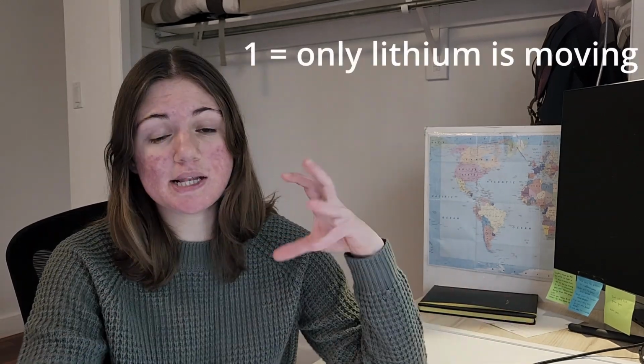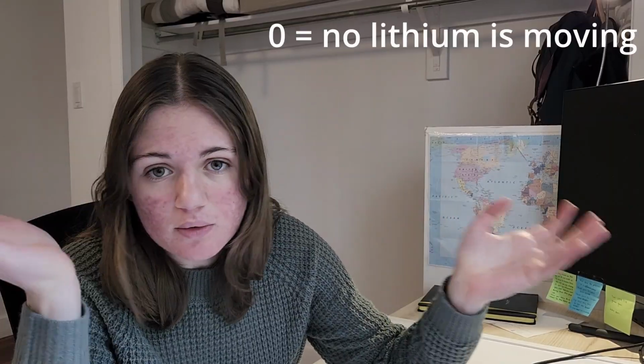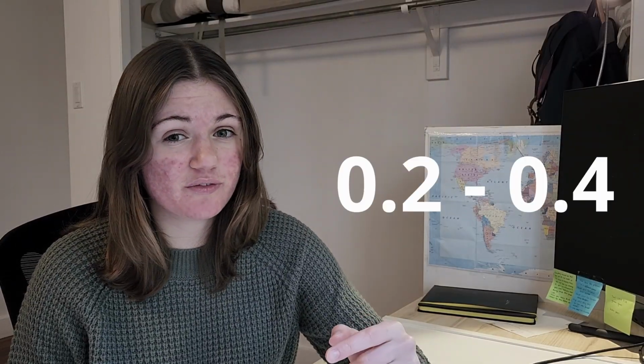The second idea is transference number. Even though we call these lithium-ion batteries, lithium ions are not the only ones doing the moving, and sometimes they're not even the ones doing the most moving. The lithium-ion transference number tells us the fraction of the current that's being carried by the lithium ions compared to the other ions inside of the battery. A transference number of 1 means that only lithium is moving, and a transference number of 0 means that no lithium is moving. Usual electrolytes only have a transference number of about 0.2 to 0.4.